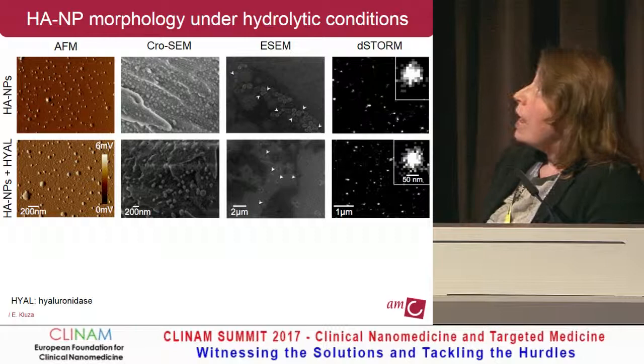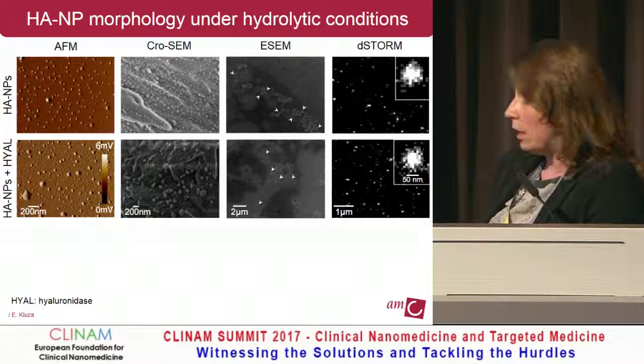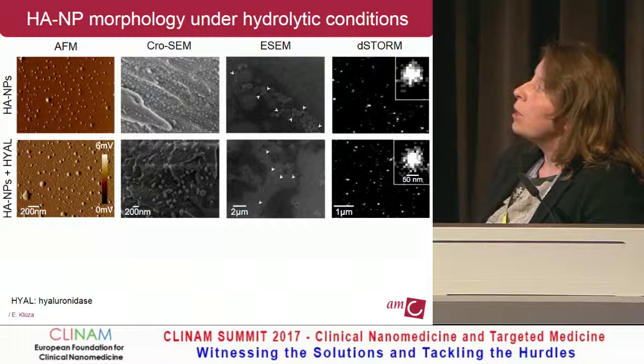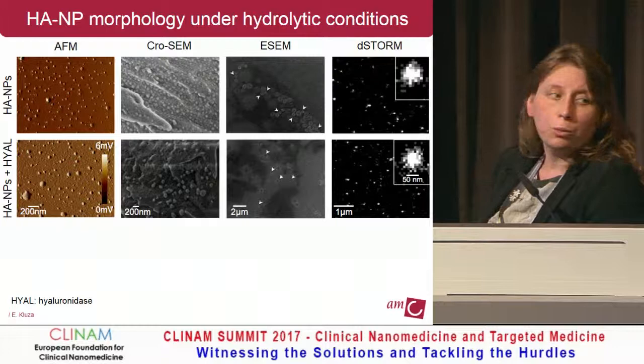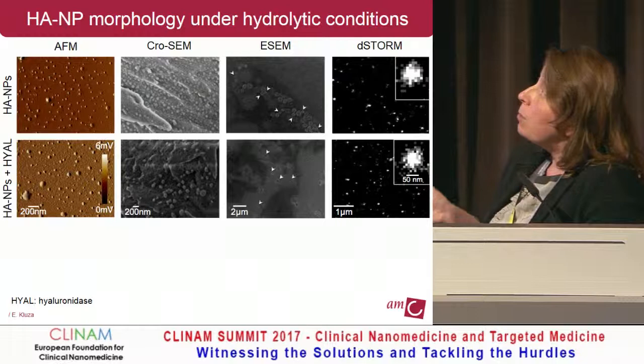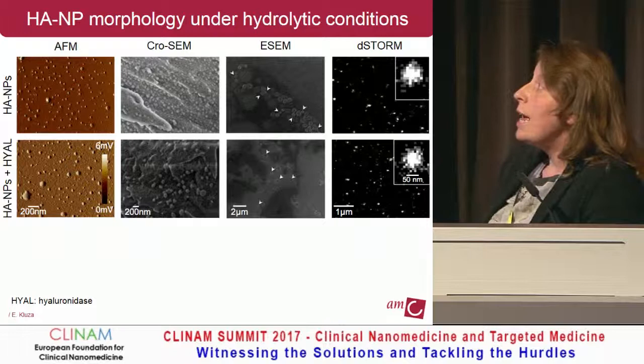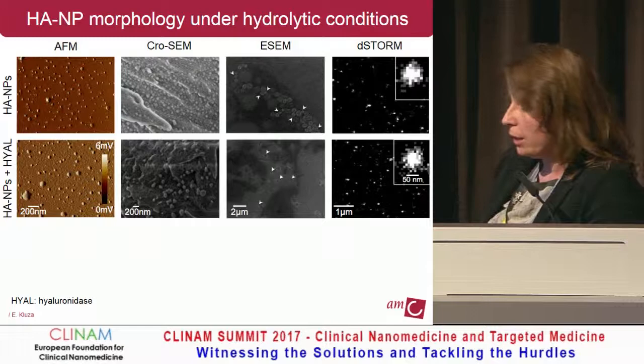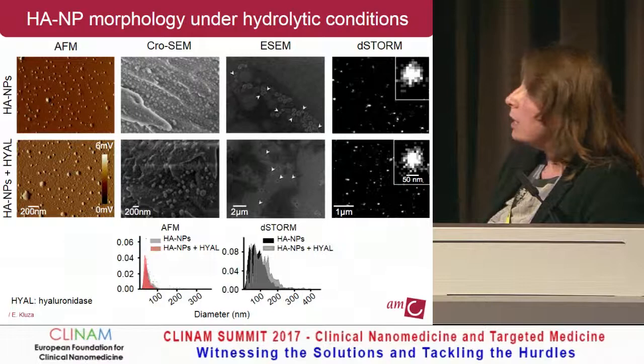Before jumping into in vivo studies, we put considerable effort into characterizing the formulation, especially the effects of hydrolysis by hyaluronidase — the main enzyme — because our big fear was that the particles would disappear after administration to the bloodstream. But all methods applied — atomic force microscopy, scanning electron microscopy, super-resolution — showed that they do not disappear and seem quite intact. The size distribution histograms also confirm that not much happens; there is a big overlap.